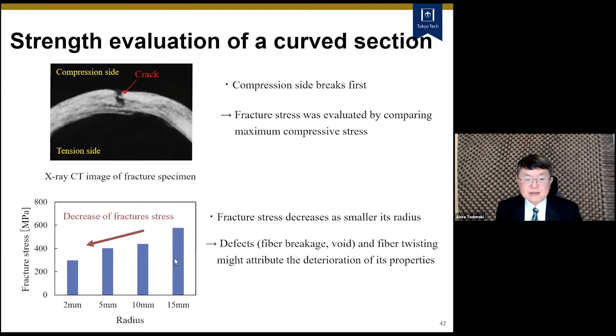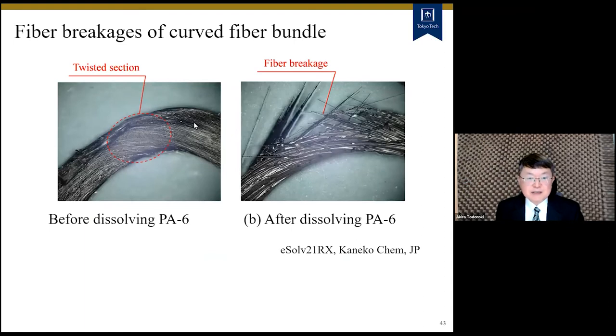And the fracture stress is shown here. When the radius of the curved section becomes small, the fracture stress becomes small because the defects like fiber breakage or void affect this strength. So we checked the fiber breakage in the curved area. In the curved area, you can see the fiber twisting here. And after this, we dissolved the polyamide 6 by using a special chemical agent. Then we can find that the fiber breakage is outside of this area.